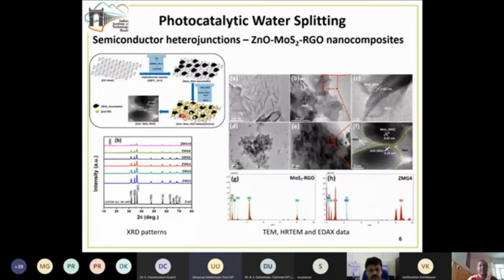So in order to do that, we did the X-ray diffraction studies, wherein we also prepared a simple control ZnO without all this, just a simple zinc oxide, this yellow colored box. And this is the X-ray diffraction pattern of this simple ZnO. And then we prepared this nanocomposite using this procedure, an in situ procedure, in different compositions ranging from 2 weight percent to 10 weight percent.